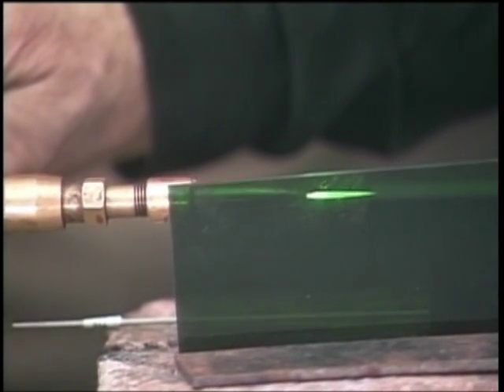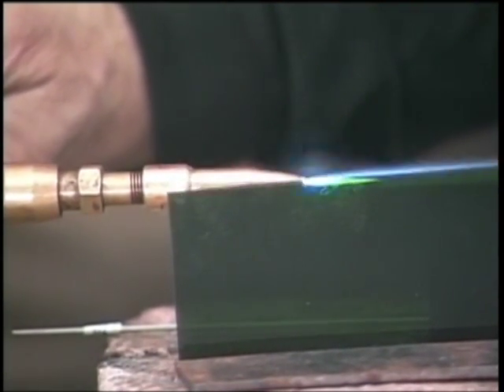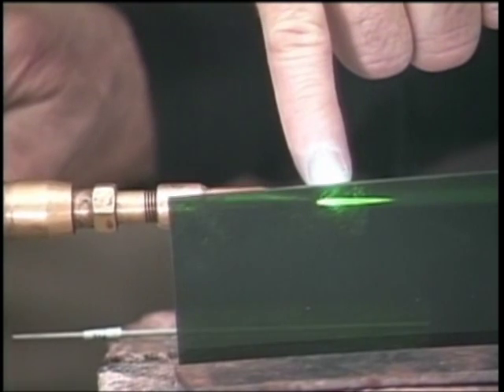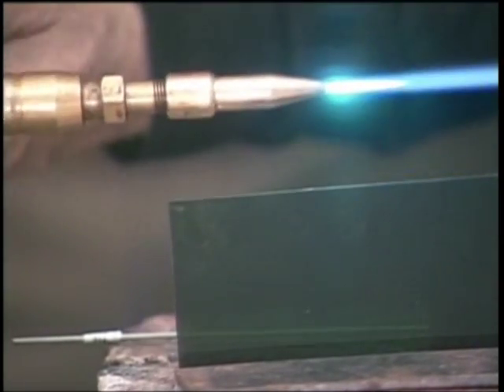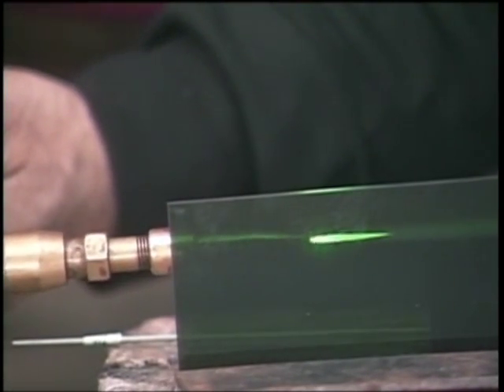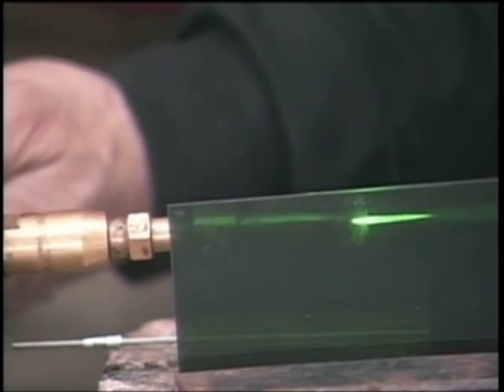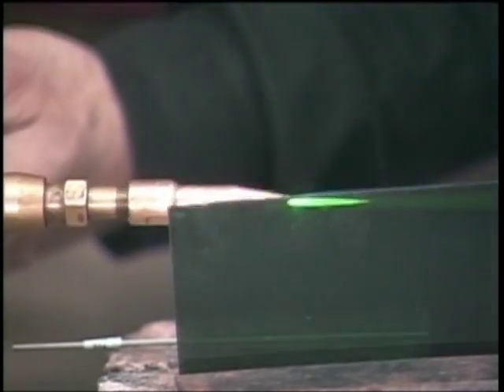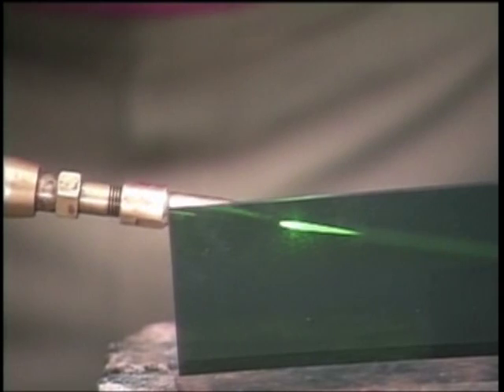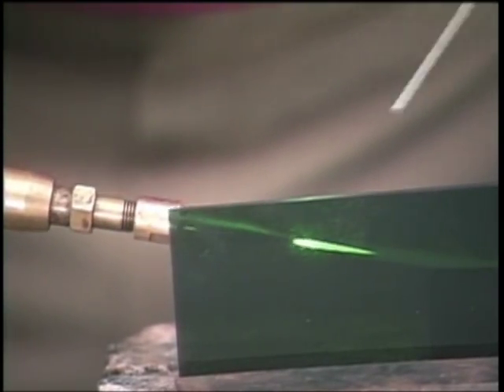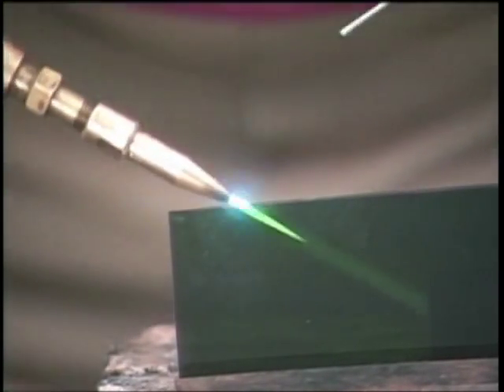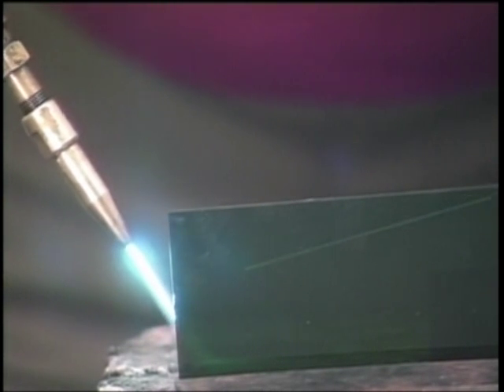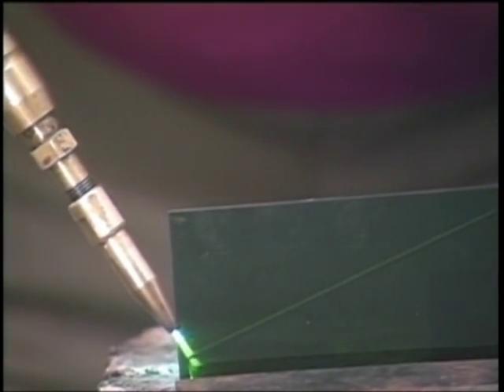The longer that cone is, the longer it is, actually the cooler it is. All right, so we run it out there about twice the length as that little inner cone right there, and that's not critical, that's approximate. But you can see that little cone on the inside, so we still weld with the little inner cone. And the reason we do that, if you get any oxygen at all in that stainless, you crystallize it, make it very brittle and weak. So that's like a little added shield. So not the outer feather, but that little small inner cone right there.